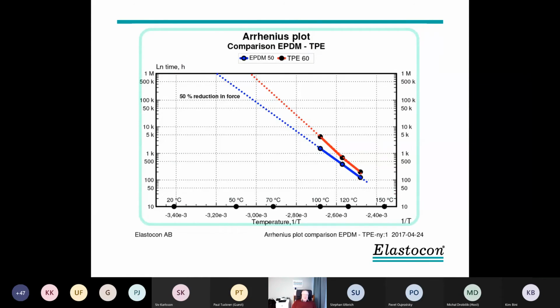The same thing with comparing EPDM and thermoplastic elastomers. They show quite different activation energies. And TPE materials are quite often better than EPDM, in fact. It depends, of course, on the type of EPDM, the curing system and other things.